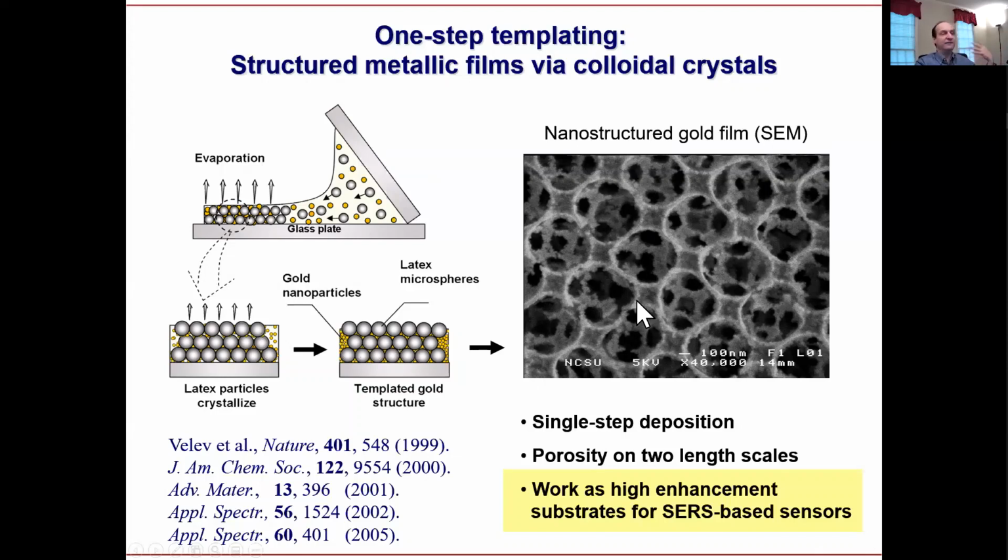And then if you have, let's say, a contaminant or chemical or toxin in water, it is going to adsorb on the gold, and then by measuring the surface plasmon, you can detect the material. That's how the sensing works. But essentially, this is a very thin layer of very high surface area gold nanomaterial.